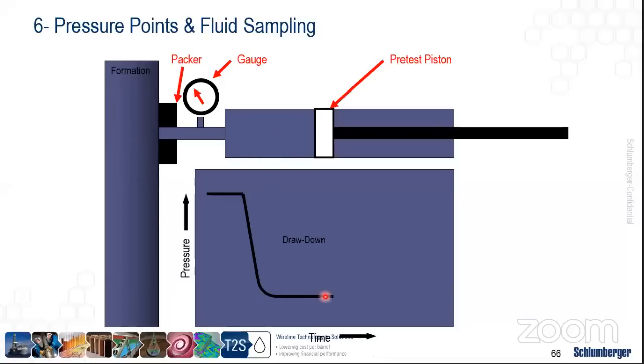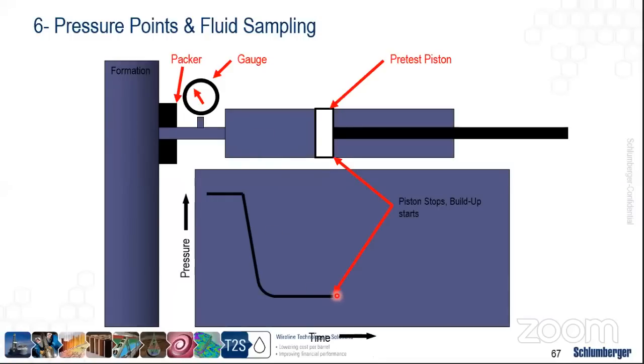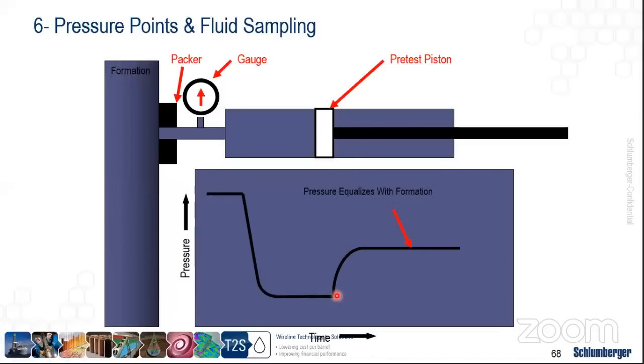We wait for a certain period of time, and then what happens is that we stop the piston, as I said, and later we start to get what we call a formation response. Once this formation response stabilizes, which is the pressure versus time, once this is stabilized, this would show the expected formation pressure in this reservoir. So anything under this, the area under this curve, let's say we have another line, this line extended a little bit more.